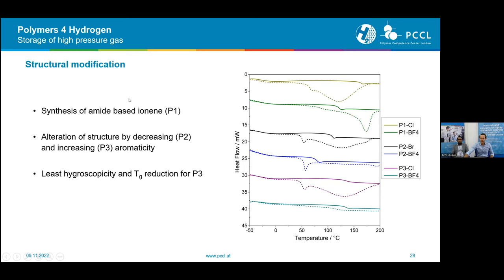And that is why we then synthesized an ionene that is based on amide linkages. This polyamide we then also once again altered by increasing and decreasing the content of aromatic groups in the polymer. And on the right, you can see the differential scanning calorimetry of those polymers before and after the anion exchange. So once again, we can see when we exchange the anion to this tetrafluoroborate that there is less residual water inside. So those polymers are not measured directly after drying, but after exposure to atmosphere and also directly after the synthesis.